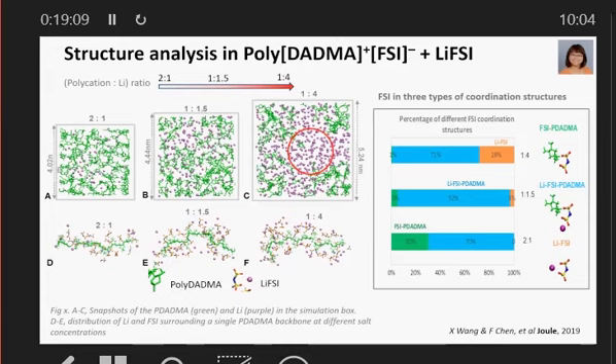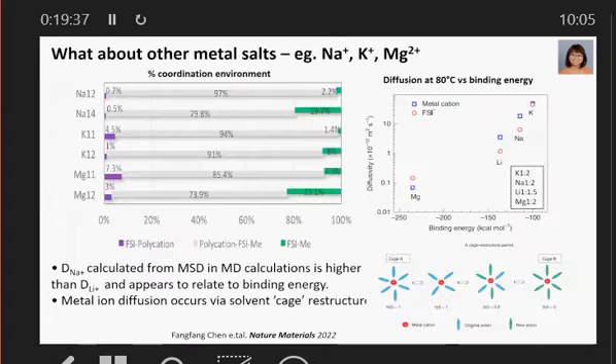co-coordination environments that dominate in that region of the optimum conductivity and transport. And as you go to higher salt concentrations, you begin to get a lot more of the LiFSI phases or regions, nanoregions, and this, of course, can be quantified, and she found in her work that there appeared to be an optimum co-coordination environment of around 1:1.5, which, of course, she didn't scan every single composition, but in the compositions she looked at, correlated with the high conductivity. Can we understand that further?